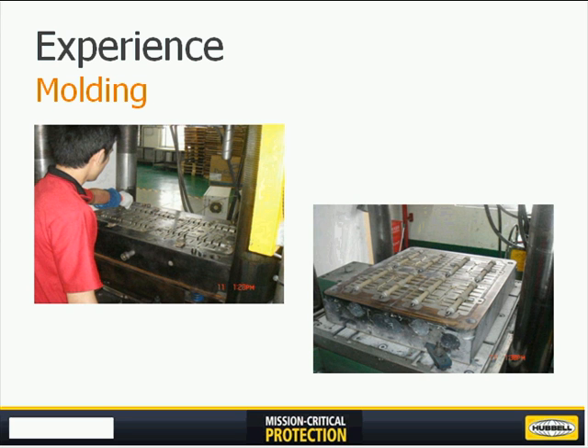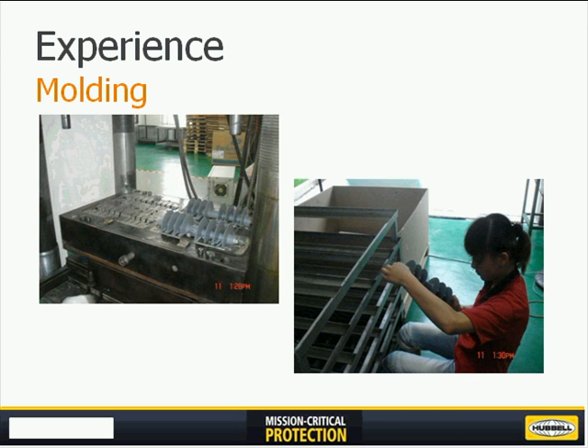So during molding, of course, if you have a part of your rod assembly which is not coated with adhesive, you can have non-bonds, and those non-bonds are going to lead to water ingress or air ingress inside of the insulator, and those flaws will, of course, be called out during steep front impulse or during temperature rise. Any air between the polymer and the rod is, of course, going to cause some temperature rise when electricity is applied to it. Again, you will see a completed insulator here in the leftmost picture, followed by an inspection of the unit.